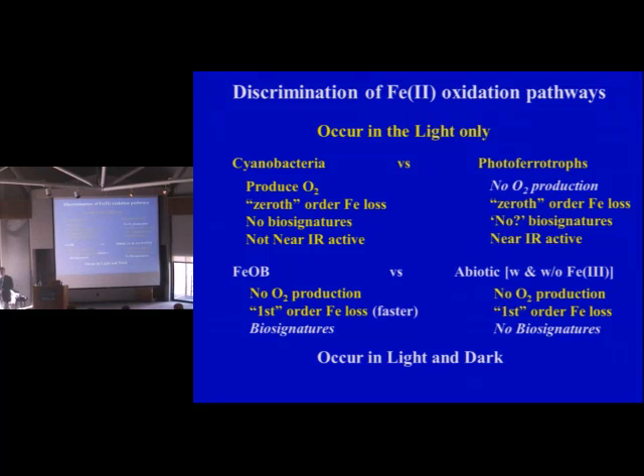It's interesting, as you pointed out, that these aerobic iron oxidizers have an optimum at a very low oxygen potential, 15, 20 micromolar. And I guess it's not an accident that's where they compete best with abiotic processes. But has anybody looked into the physiology of how they actually optimize their activity at such a low potential? Not yet, as far as I know.